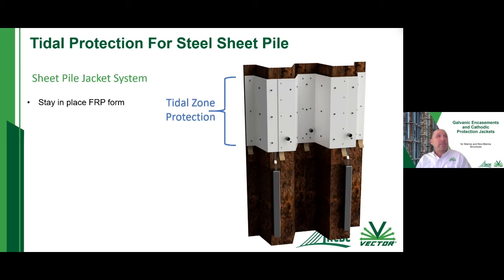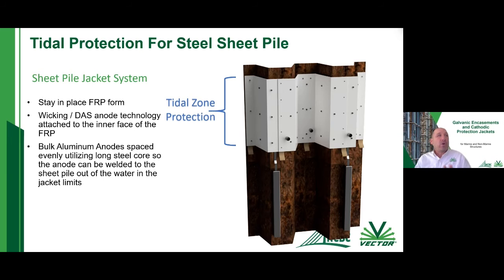And then you're going to throw in some anodes within this stay-in-place form. So this is the tidal plus anode. It's going to rely on that wicking technology, making sure to bring the salt water up to keep that anode in an active state. And then everything that is below that jacket, you're going to want to put an anode on it. So in this case here, the anodes were actually attached up in the jacketed zone. This just saved the contractor from actually having to use divers to weld the anodes on. But anodes can also be welded on traditionally, like I'd shown you in the previous photograph. So just regular bulk anodes that are just welded to the sheet pile wall.